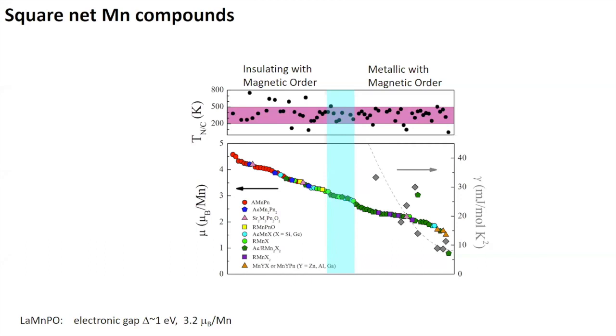Alternatively, if you look on the right-hand side of the diagram, you can see that there are compounds where the moment is only a few Bohr magnetons per manganese, and these compounds are typically correlated metals. So for the purpose of this work, we focused in on a particular compound, which is that yellow box. This is lanthanum manganese phosphorus oxygen.